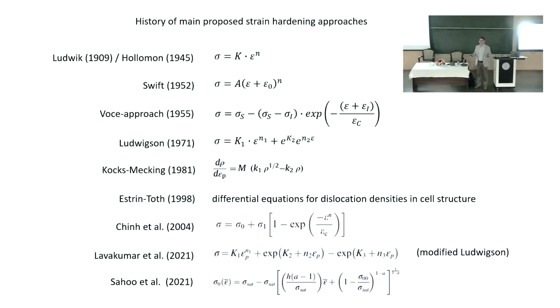This is just a function which can describe, not fully, but some part, usually the initial part, and especially stage 3 - stage 3 can be described with such kind of function. So all this is fitting. Swift, 1952 - I was born in 1952 - a little bit modified, you see, by adding a constant here, basically about the same thing.